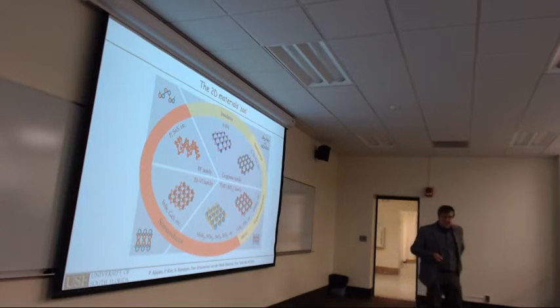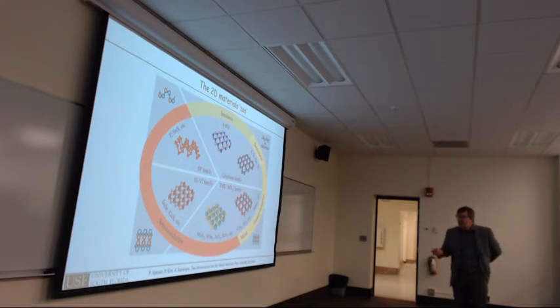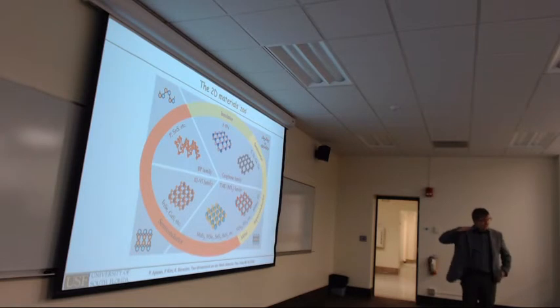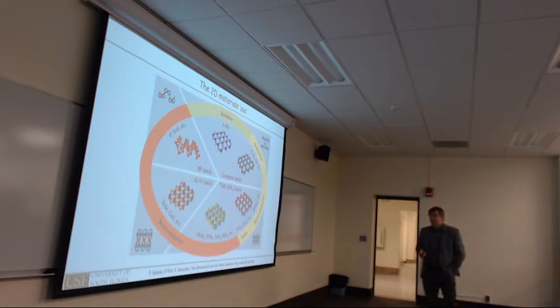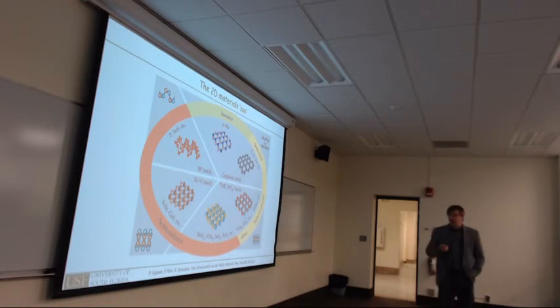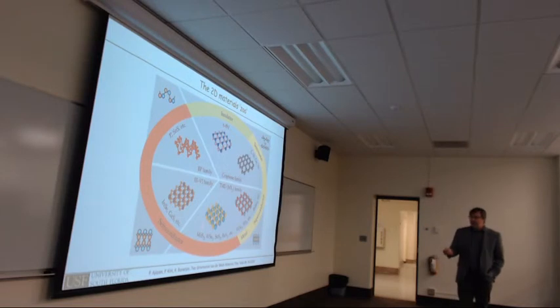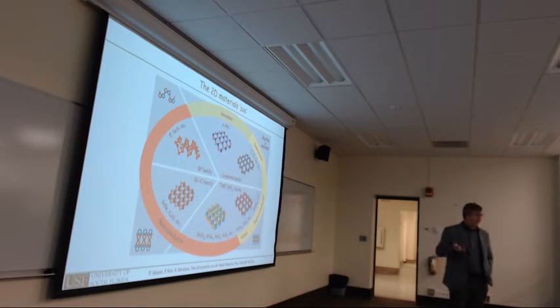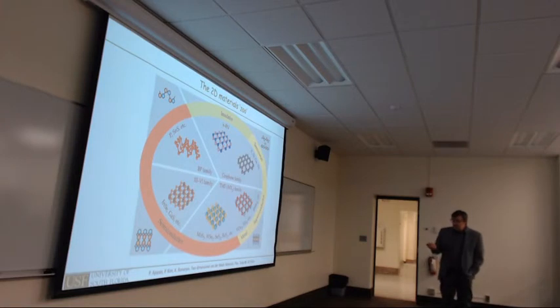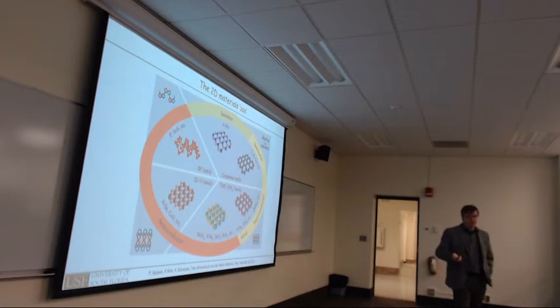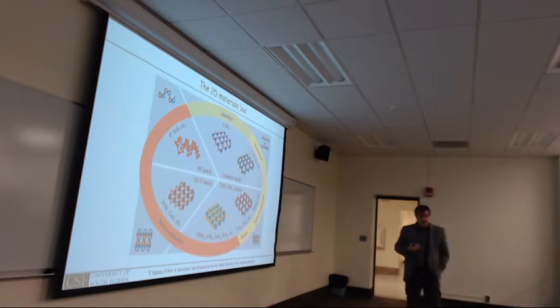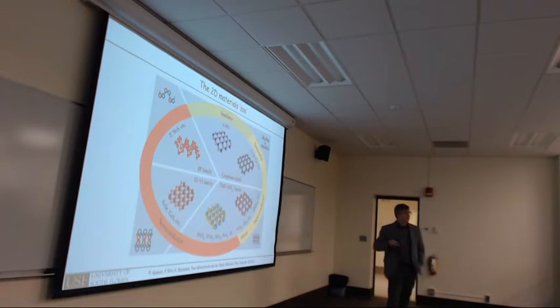The materials class I want to talk about is transition metal dichalcogenides, which are essentially three-layer materials where you have a metal layer sandwiched between two layers of chalcogens, so either sulfur, selenium, or tellurium. What's interesting about that family is that it spans a wide range of properties. The most famous or most recognized ones are the semiconducting ones, like molybdenum sulfide. But there are also metallic ones. So I'm doing work on vanadium selenide and titanium selenide, which are metallic, and even superconducting ones like niobium selenide and so on. Especially the metallic ones have a lot of interesting many-body physics problems like superconductivity or charge-density wave